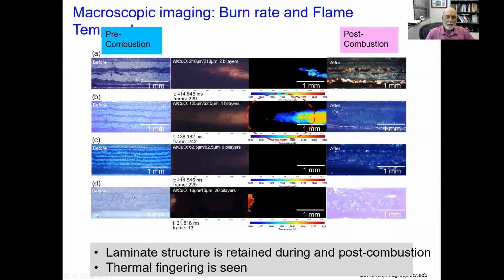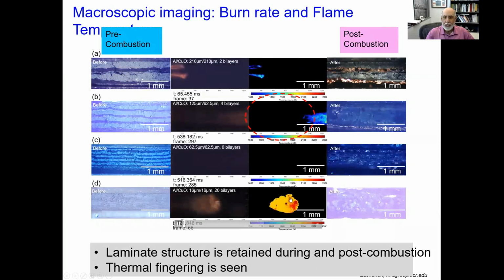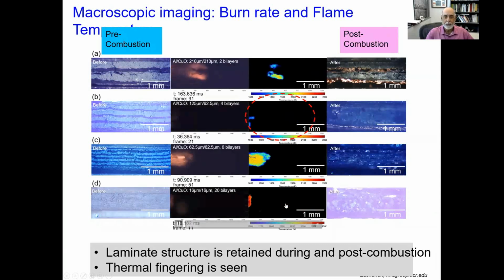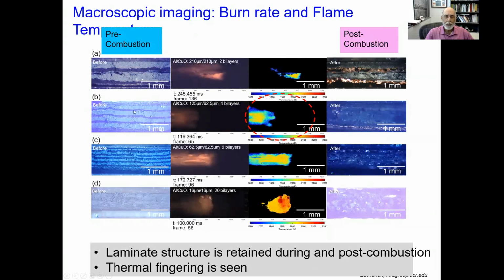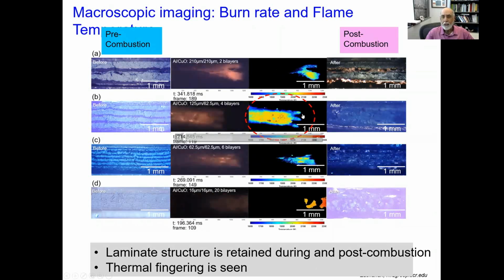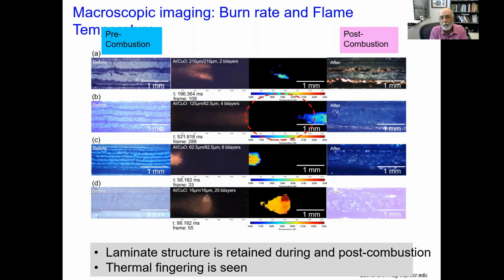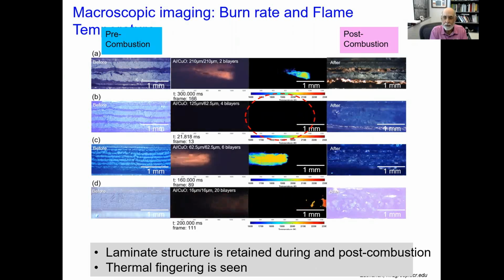So when the layers are very closely spaced, the reaction front looks sort of homogeneous. But when they are separated with higher spacing, you see this fingering structure. And that's going to be related to the mass transfer limits associated with moving oxygen from one place to another.